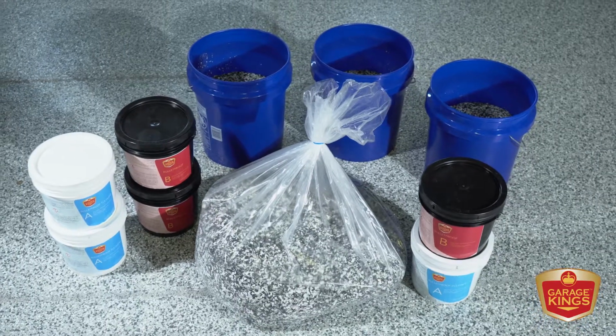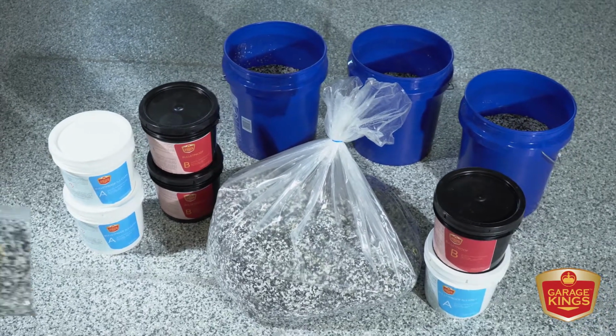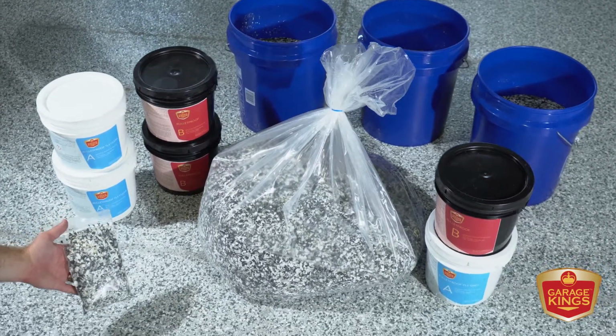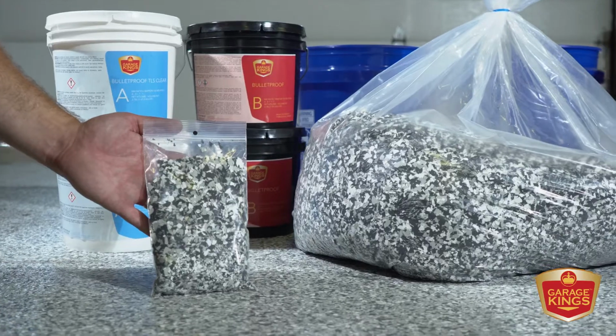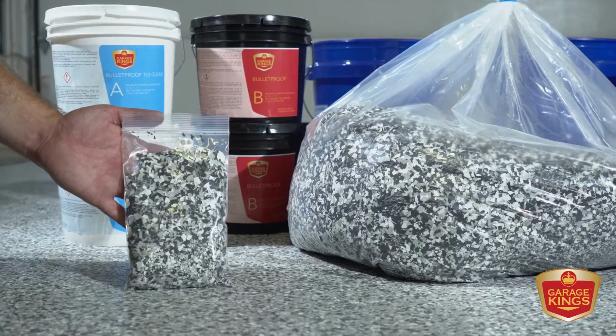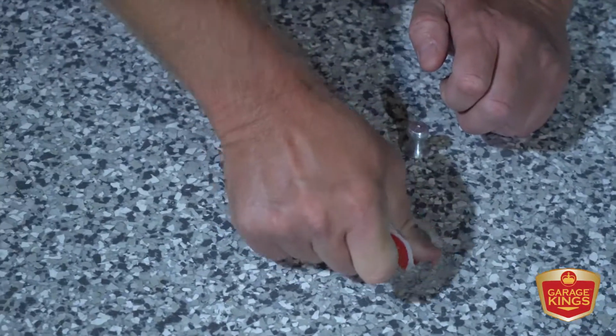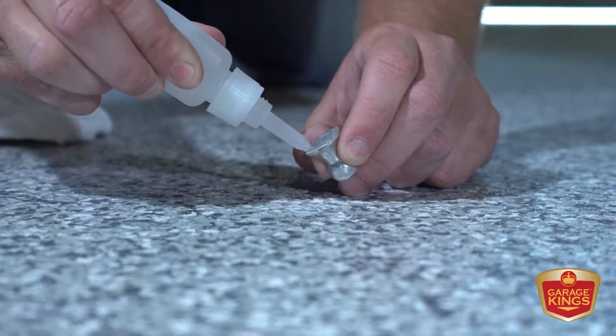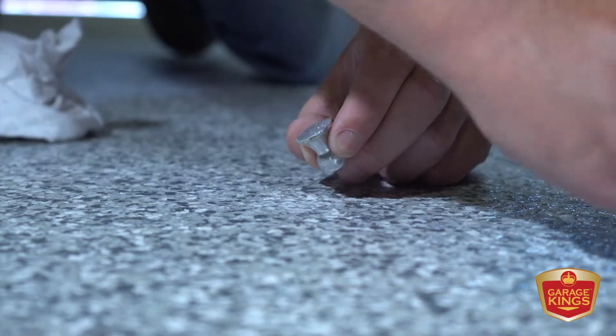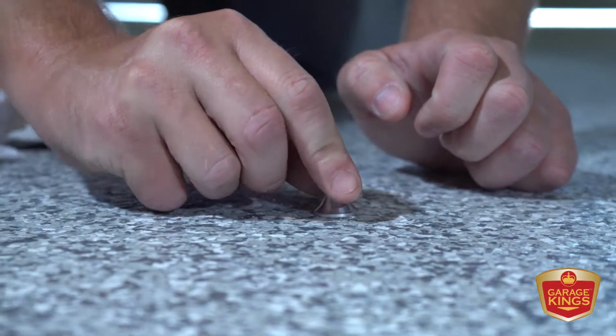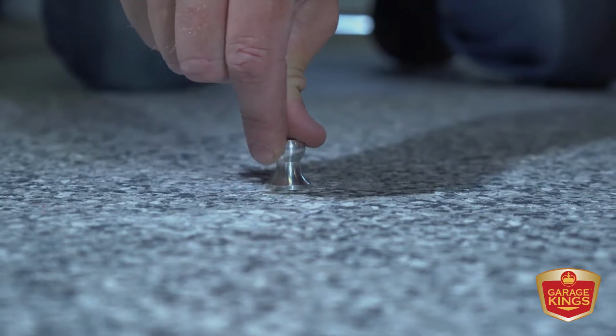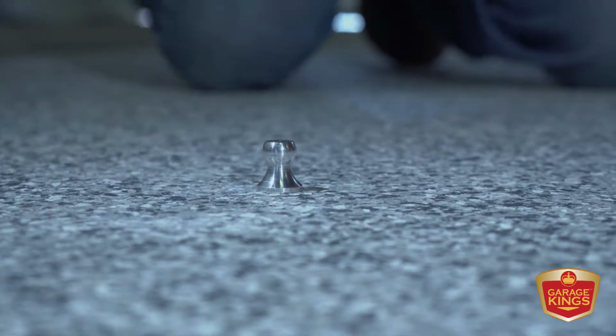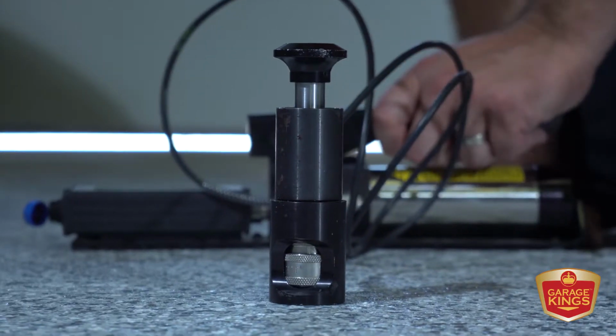You can save yourself the headache by going with a professional like Garage Kings, where we'll do it right the first time, and we back that up with 21-year adhesion warranties, and we can show you our adhesion strength through the adhesion test that we're going to demonstrate today. An adhesion test is the industry standard on whether or not a coating actually bonds to the substrate. We perform that to show that our coating is not going to fail prematurely and that concrete will break before our coating lifts from the concrete.